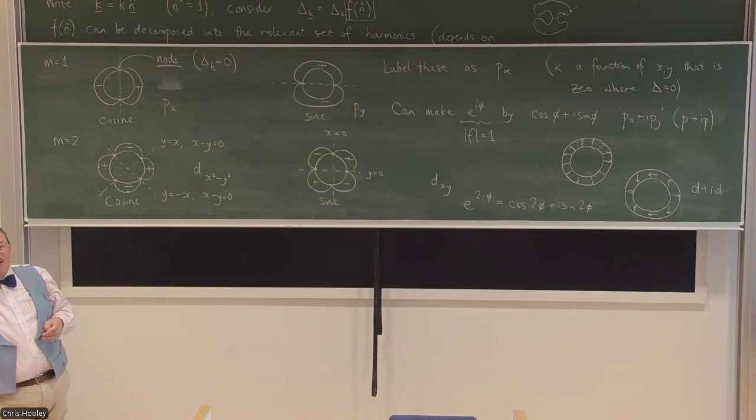No, right, and yeah, okay, in most materials that's what you have to do. But they're not degenerate in 2 dimensions, right? But you can find a symmetry protected degenerate combination in 3D, d_yz plus i d_xz, in a tetragonal material. Yeah, and this is to do with higher dimensional irreducible representations in the group theory language.